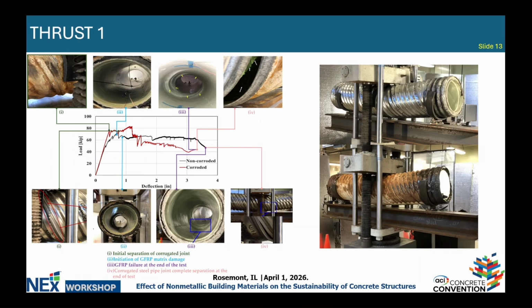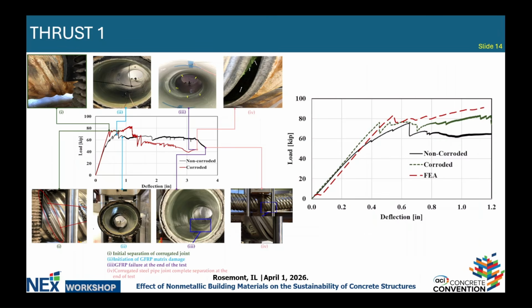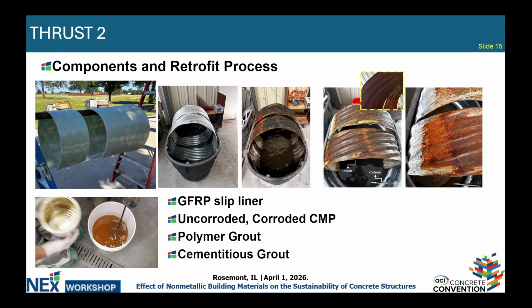So overall, if you look at the results of a non-corroded and the corroded, we do see some good composite action being held and carried forward till the end of the test in both systems. And the corroded one, though there's damage to the steel pipe, you don't see too much of a deterioration in terms of load carrying capacity. A finite element model was also created, which agreed well with the experimental results as well. So again, an in-depth study can be found online in the journal paper and the dissertation.